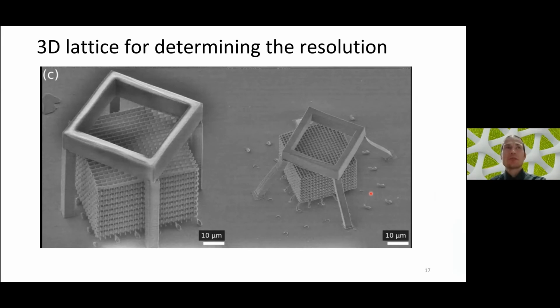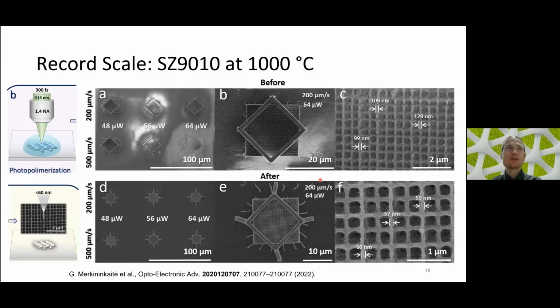And to determine the resolution or also the geometry quality, the 3D lattice remains the best, or at least one of the best structures to make, because it covers all the individual features, the pore size, the filling factor, and similar parameters, as well as overall shape. And by optimizing the writing parameters, which can reach down to 100 or near about 100 nanometers for raw, pristine material, after pyrolysis it's downscaled to 60 nanometers or so, in a quite reproducible manner, and the shrinking is symmetric in all dimensions.